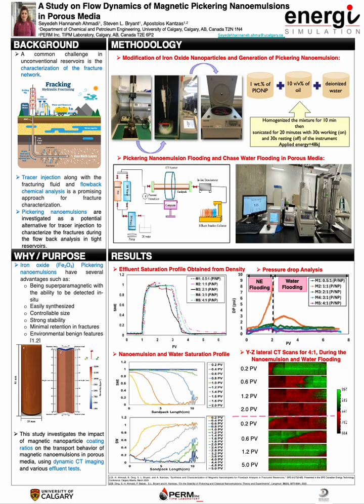The type of nanoparticle that we use in this research is iron oxide nanoparticle, and the advantages of using this nanoparticle are being superparamagnetic with the ability to be detected in situ, easily synthesized, controllable size, strong stability, minimal retention in fracture, and environmentally benign features. Consequently, this study investigates the impact of magnetic nanoparticle coating ratios on the transport behavior of magnetic nanoemulsion in porous media using dynamic CT imaging and various effluent tests.